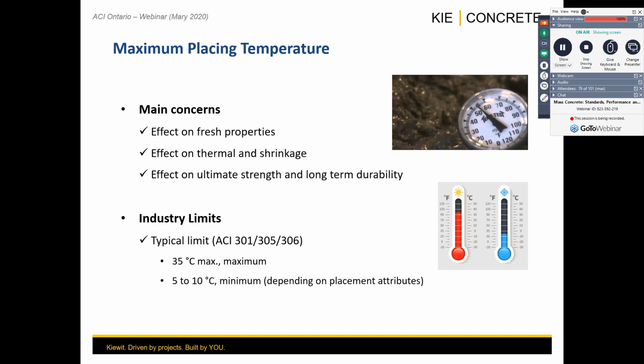In the actual placement, what are going to be the limits from a shrinkage perspective, the risk from cracking perspective. All of those things are going to be impacted by the placing temperatures, and also the ultimate strength and long-term durability. In the case of ultimate strength, if you have a very hot mix and you allow that to happen at early age, you're likely not going to achieve the maximum ultimate strength that you want at later age. So there could be some impacts into that.